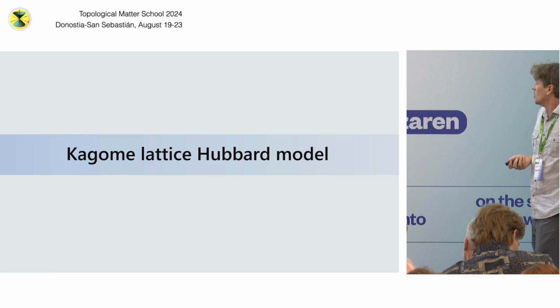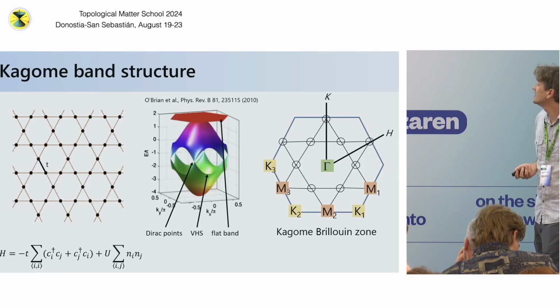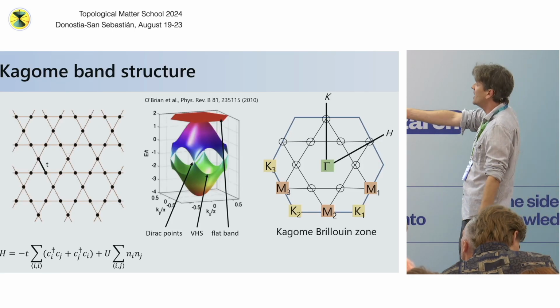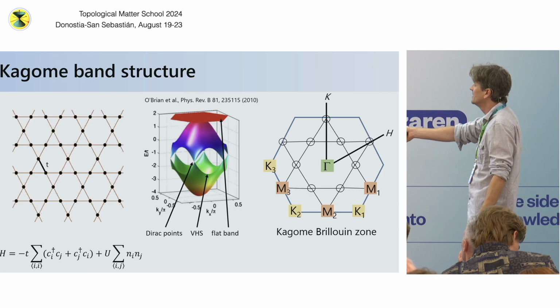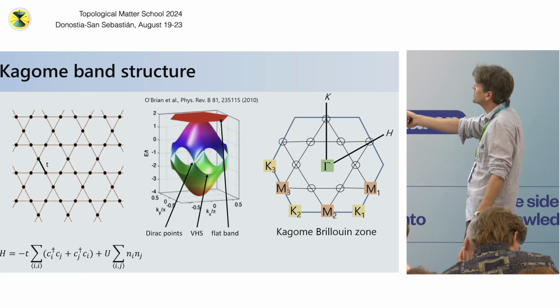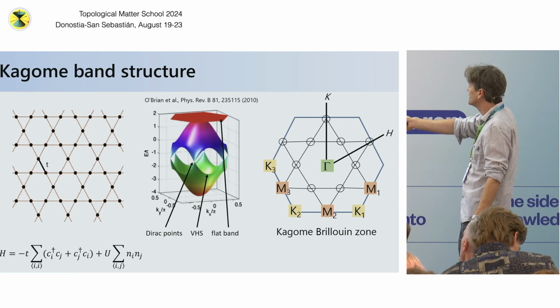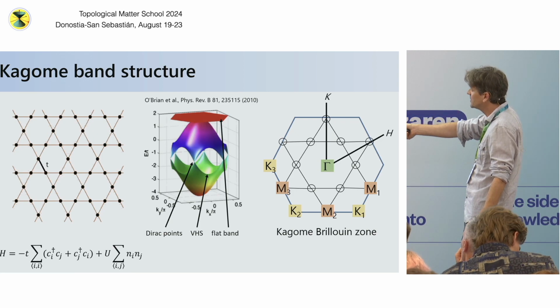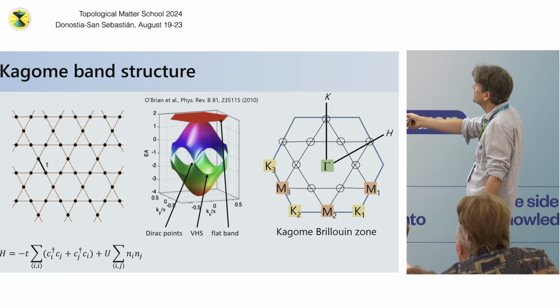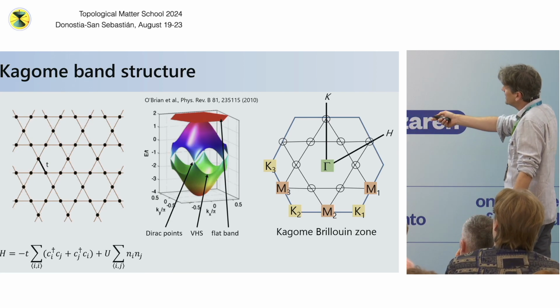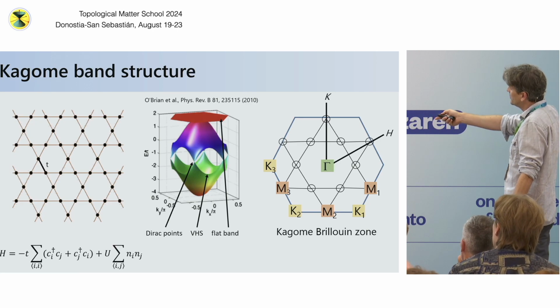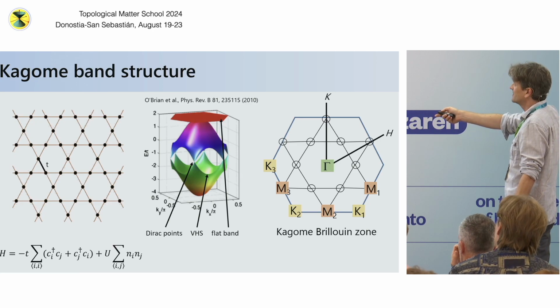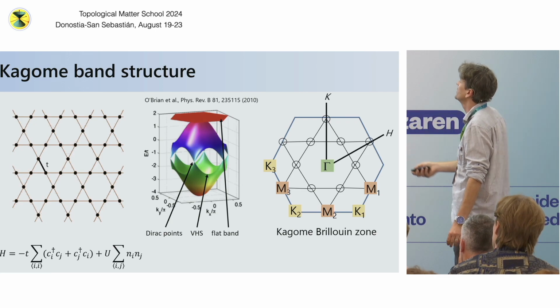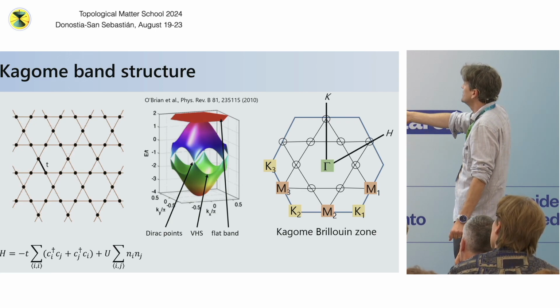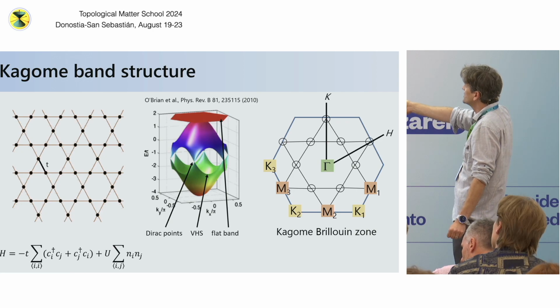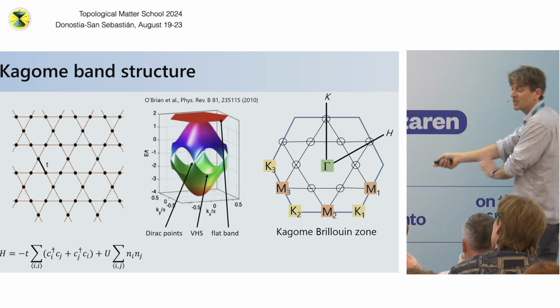Okay, so why is the Kagome lattice interesting? If one thinks about just hopping across a Kagome lattice, in a tight binding model with a single orbital, you get a three-band model, and the band structure is the following. You get a dispersion of the bands up to these Dirac points, these Dirac crossings that Alan talked about early in the morning. You get a series of two saddle points, and then you also get a flat band, okay?